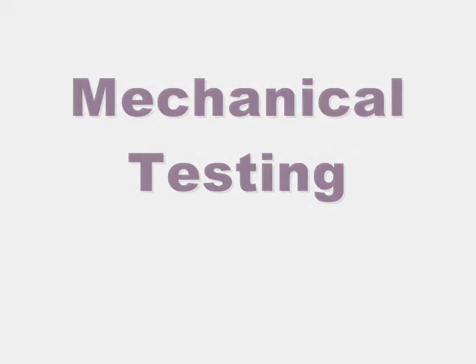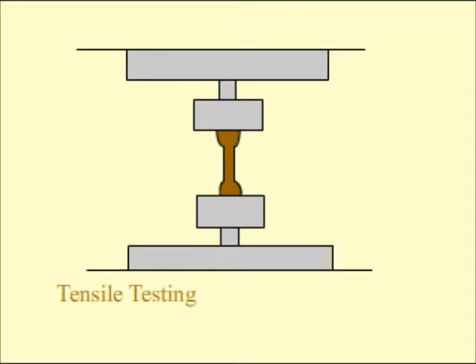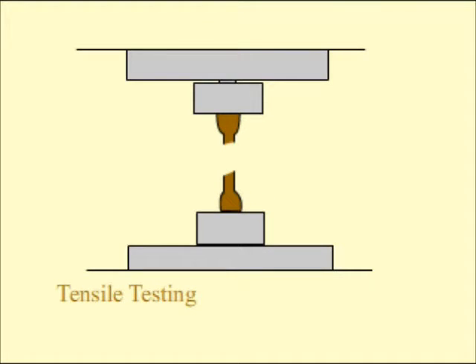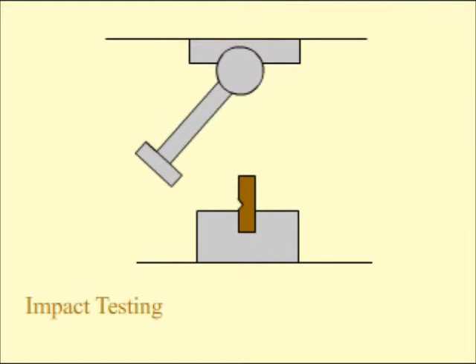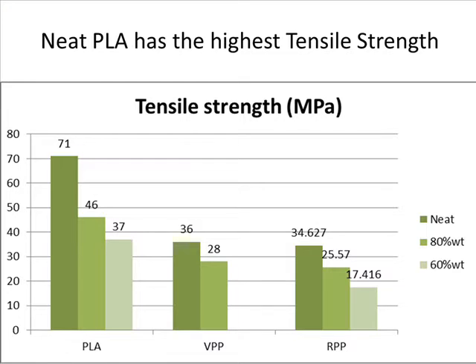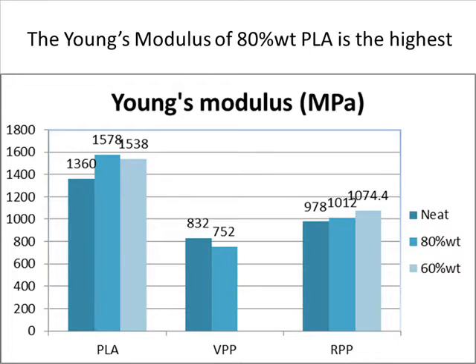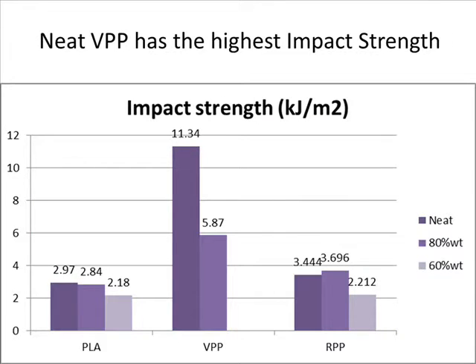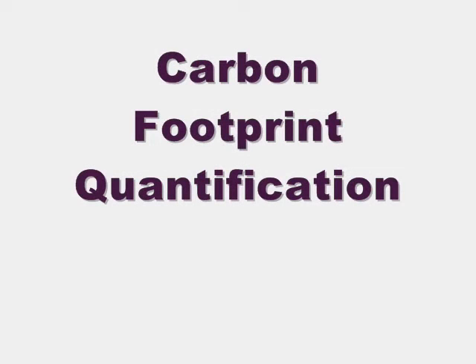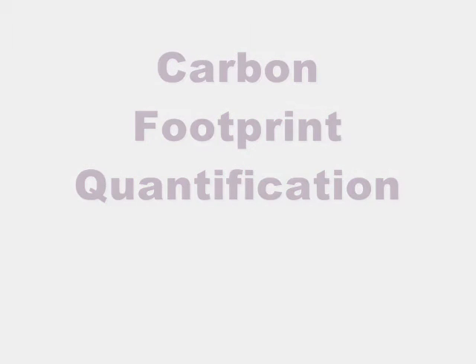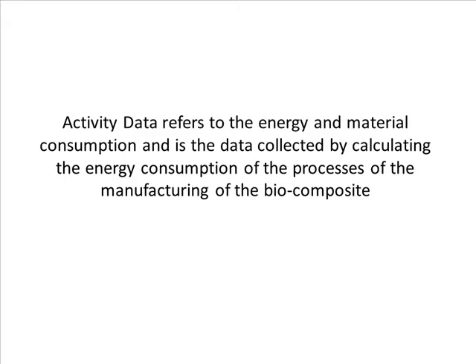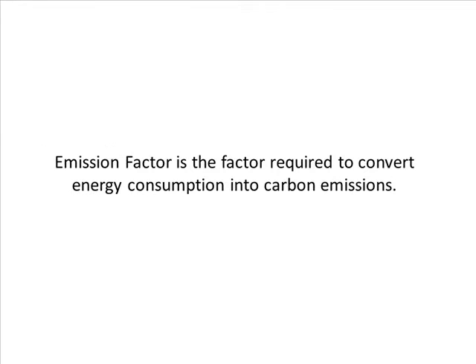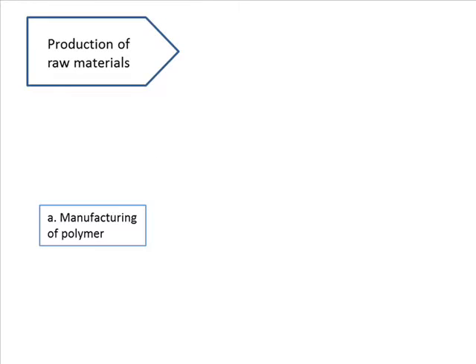Under mechanical testing, the tensile strength, tensile modulus, and impact strength of the bio-composite materials were tested to ensure that the materials are strong and flexible enough for commercial usage. The results obtained were then compared to that of the neat polymers to analyze the practicality of replacing the neat polymer materials with the bio-composite. Two main data types for carbon footprint quantification are activity data, for example, energy and material consumption, and the emissions factor, for example, the conversion of activity data into carbon footprint.